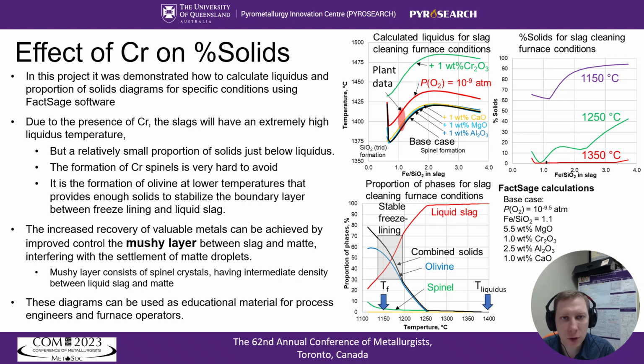In the course of this project, we demonstrated how to calculate the liquidus and the percent solids in the slag. The results of plant sample analysis and process modeling were used to specify the conditions for the calculations. Due to the presence of chromium in the slag, the liquidus is extremely high, but the percent solids just below the liquidus temperature increase very slowly because the solids are basically chromium-based spinels. Only when olivine starts to precipitate out, the combined percent solids are significant enough to maintain the stable freeze lining.